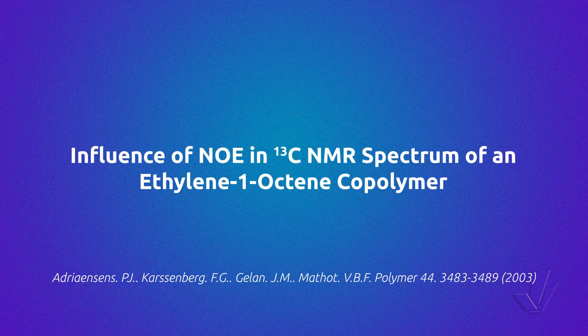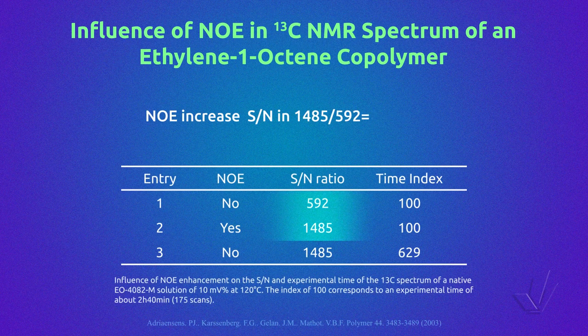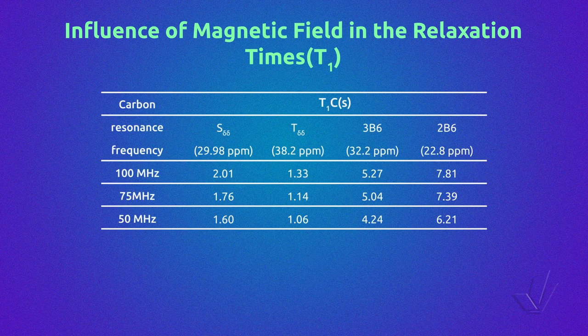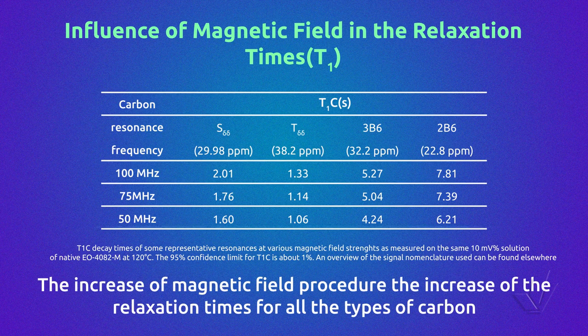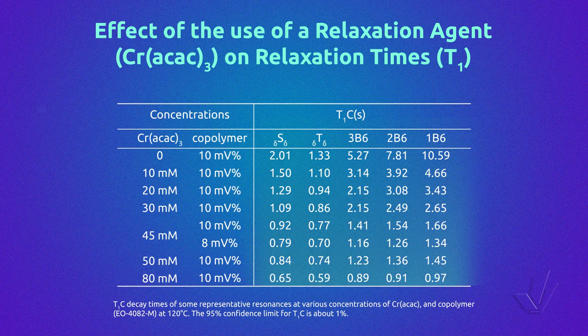In a very interesting work by Anderson and co-workers, they acquired the spectrum of an ethylene/1-octene copolymer without NOE and with NOE. They found that NOE increased the signal-to-noise ratio by 2.5 and reduced analysis time by a factor of 6.3, as seen in the table. They also studied the influence of magnetic field on relaxation times T1. The increase of magnetic field produces an increase in relaxation times for all types of carbon, but this increase is not very significant. They then studied the effect of using the relaxation agent chromium(III) acetylacetonate on relaxation times T1, and found that relaxation times decrease with increasing concentration of the paramagnetic substance.